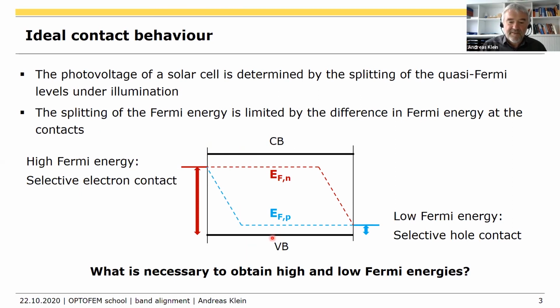So the holes in the valence band, they can of course go to this contact, but they would also win some energy when going to this contact. So this does not give the selectivity. Usually, if you want to make the contacts selective, you have to add an additional barrier here, a blocking layer for holes, or on this side, a blocking layer for electrons. This is not shown in this graph, but that's in principle the secret which makes the